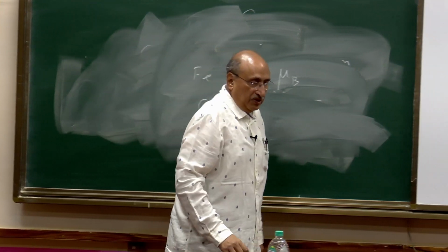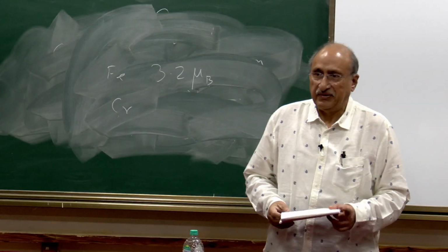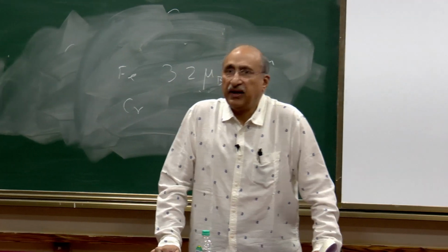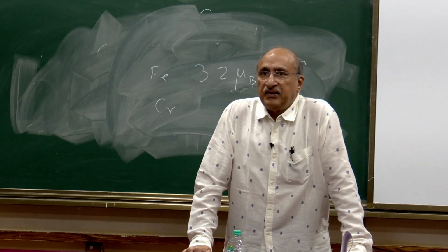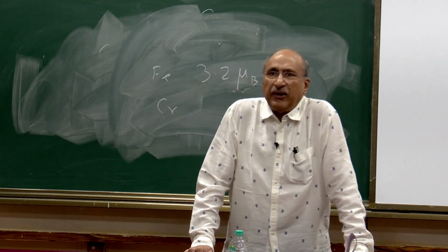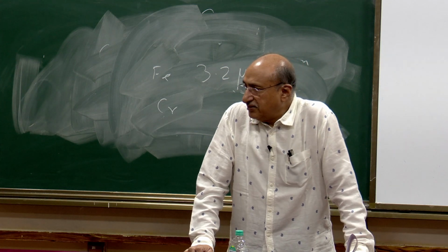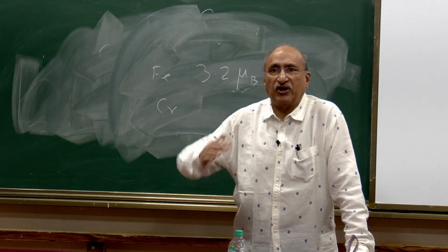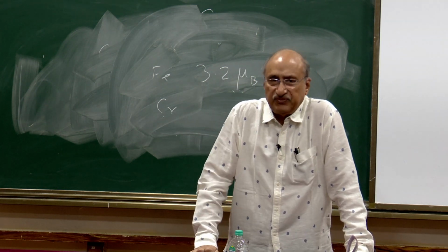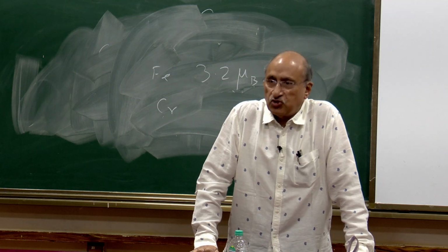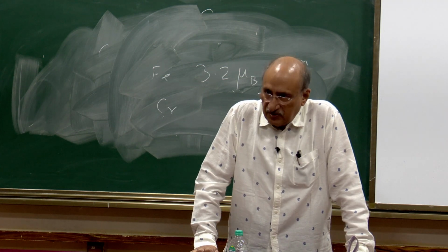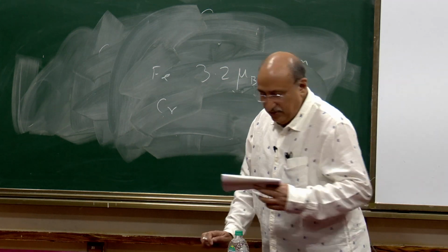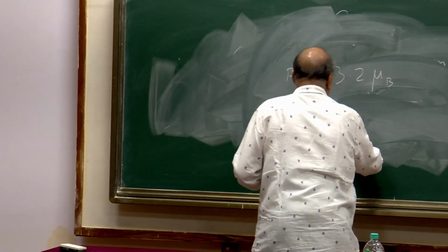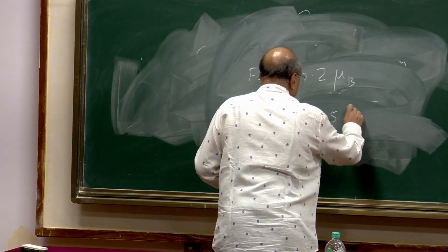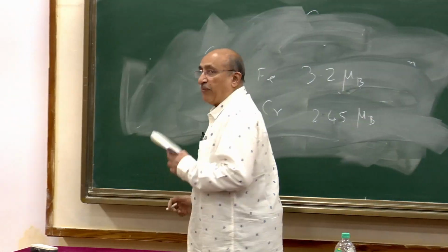Then chromium. Chromium is a very complicated material in a bulk form. It's generally referred to as antiferromagnetic, but actually there is a spin density wave here. It's not really antiferromagnetic in that sense. It's a comparatively more complicated material. And Freeman's paper predicted that this will have a Bohr magneton of 2.45, and it will become ferromagnetic.